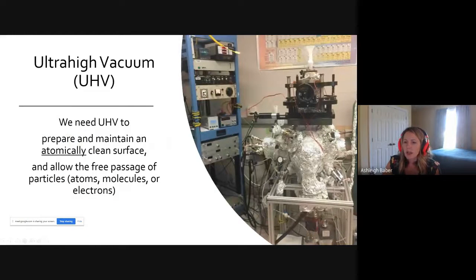So here again is our ultra-high vacuum chamber. Of course, I have to talk about UHV at an AVS meeting. And so we work under ultra-high vacuum to keep our surfaces very clean. You can see on the left-hand side, we have Auger electron spectroscopy, and we mainly focus on temperature program desorption, which I'm not sure if everyone is familiar with, but I am going to talk about it just in case not everyone is up to speed there or hasn't heard of it yet. But you can see we have some high precision leak valves on the chamber, so we're able to dose in molecules of interest onto our gold and silver surfaces. And when we are running experiments, we have a base pressure of around 5 × 10⁻¹⁰ torr.